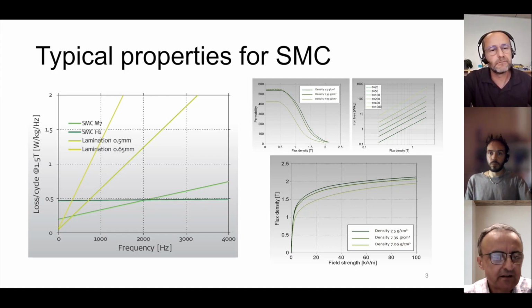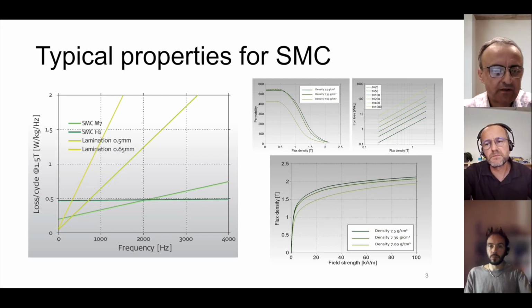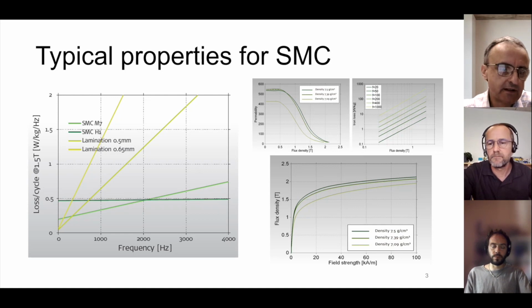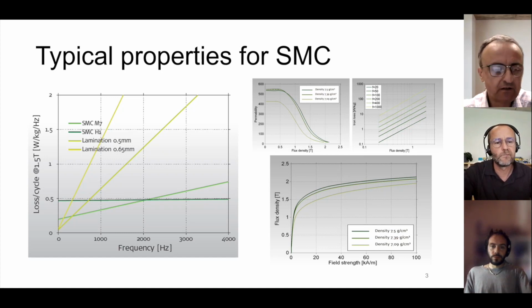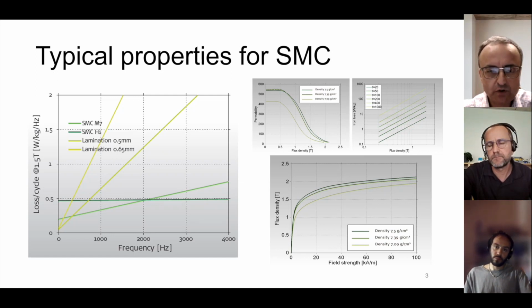Well, let's say it's very interesting from one point of view to see how effective the insulation that you mentioned can be. Indeed, looking at the properties on the left for material H1, we can see that in the graph, we have reported the losses per cycle. Indeed, the energy lost in each cycle is practically constant with frequency, at least in the range that is analyzed here, which means that actually the insulation between the particles is very effective, because in practice we only see hysteresis losses there.